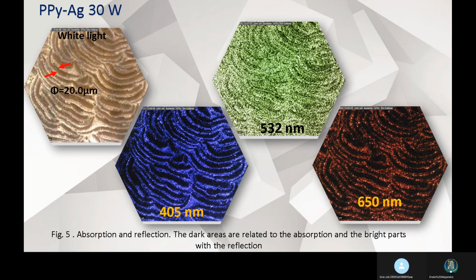Finally, polypyrrole and silver composites at 30 watts has presented the most interesting morphology with white light, and it was possible to see semi-spherical groups with 20 micrometers of diameter. The material was sensible in all lights, but the highest sensible was with blue light.